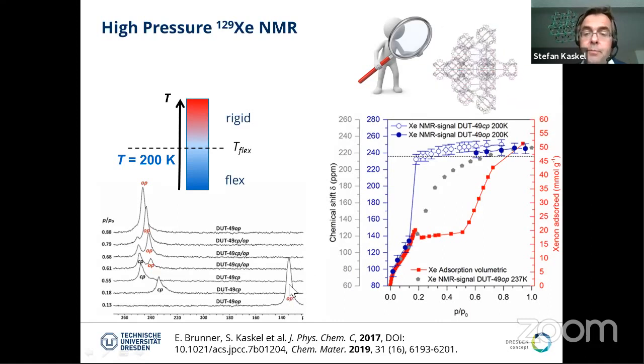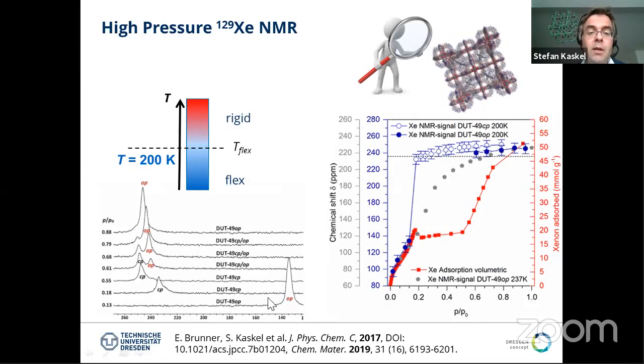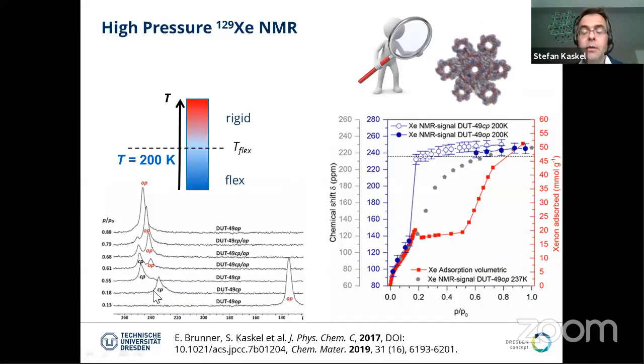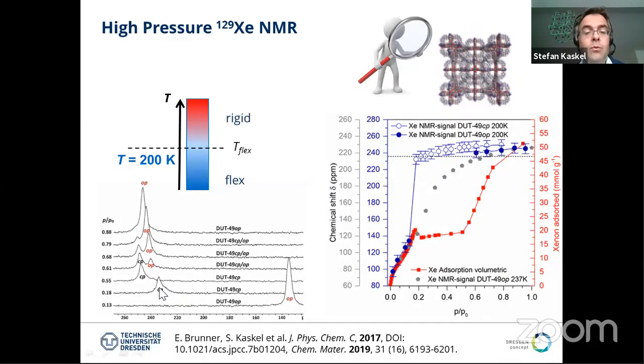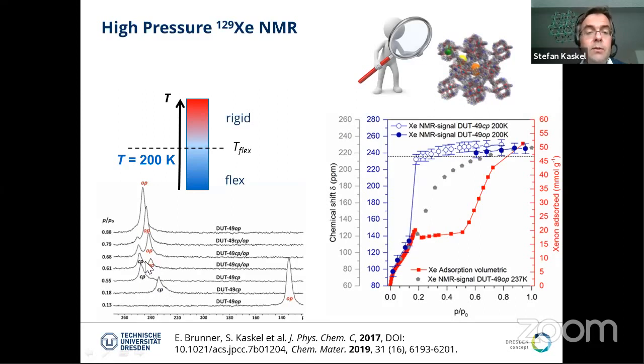So we see initially at low pressure, the chemical shift is at this position here. And then once we increase the pressure and we have the structural transformation, there's a huge shift of the chemical signal, because suddenly we move from a mesoporous to a microporous system. And then due to the pressure change, the signal is shifting. And here we can even see two signals because we have a coexistence of the OP and the CP phase. And then at high pressure, the system is completely open and we only have the open pore phase.